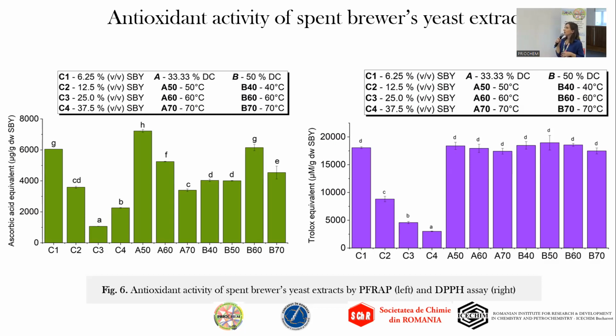However, FRAP showed a more comprehensive difference between the samples in comparison with the DPPH, meaning that we observed that at an optimal temperature of 50 degrees Celsius, the antioxidant activity was the highest. There is a descending trend of antioxidant activity when the temperature is increased at 33 duty cycle. Things are rather different with the 50% duty cycle, since the antioxidant activity seemed to rise along with the temperature.